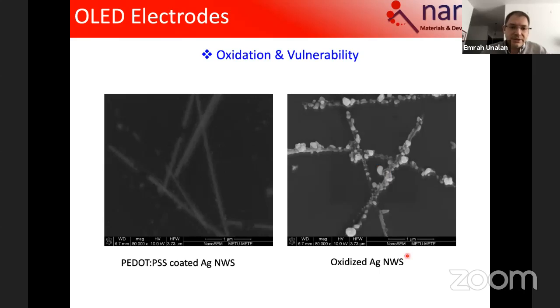And PEDOT:PSS is a problem. In 2014, Sigma Aldrich introduced a non-acidic version of PEDOT:PSS. But if you use a typical conventional 4083 or PH 500, these are acidic PEDOT:PSS. And as you see, if you keep them long enough, the nanowires start getting etched. Even if you don't put the polymer, if you leave the nanowires on the bench, you start getting some dimples on the nanowire. So certainly there is a stability issue.